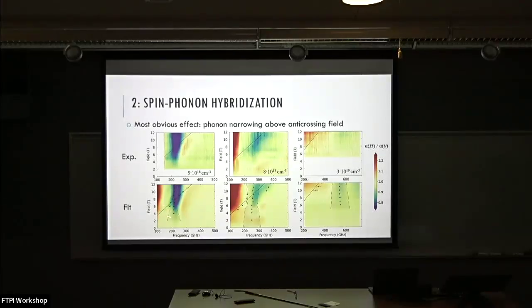And this is actually shown in the fits. So with these lines, the width without field is around 100 gigahertz here. And then it narrows by almost 50%. So this is a huge effect. And this narrowing seems to onset roughly around the center here.